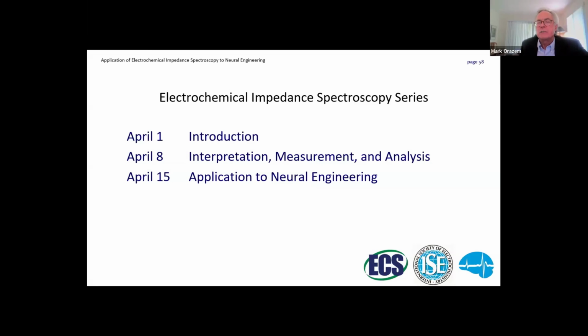The typical way of explaining a constant phase element, the units come about because you have the imaginary number times frequency raised to a power, and so the units have to account for that. The CPE itself, back when I was learning impedance, we mostly considered it as a fudge factor, just a way to make our data look better. So it was controversial. It really was, and a lot of people refused to use them on first principles. But the fact is that the systems we're studying are really not ideal, and so the constant phase element comes about from a distribution of time constants.